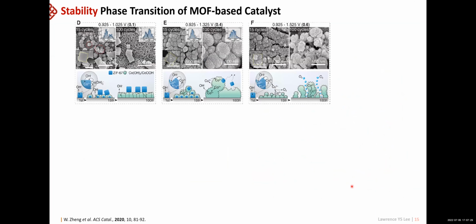So we took the SEM image after two different cycle numbers, after 15 cycles and 100 cycles for each of the three potential windows. As you can see, the initial cube shape has already changed, into something more like nanosheet arrays, even within the low potential windows. So we interpreted that those ZIFs that are in contact with the electrode surface will go through interaction with the hydroxide species, and they actually change to some other species. And that is more severe as you move on to higher potential windows. And if you go to the OER range, because of the oxygen bubbling, we can even see the cracks.